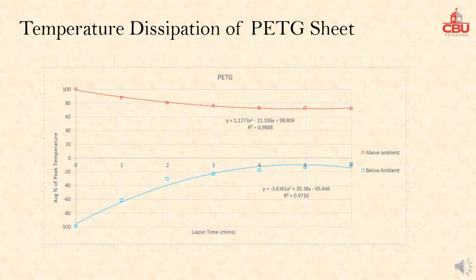A temperature dissipation rate for PETG was produced, similar to that for corrugated paperboard in a previous study. Two curves were plotted, one for conditioning temperatures above ambient, and another for those below ambient.